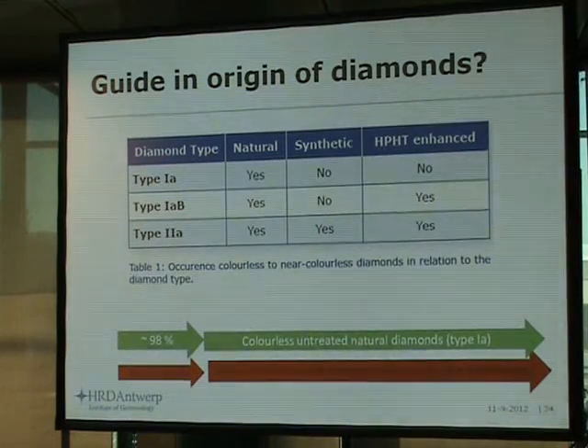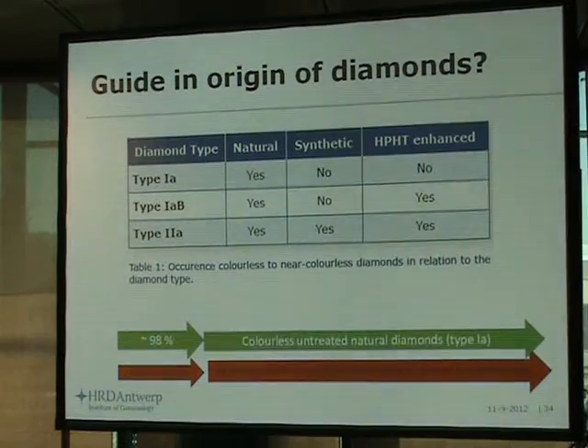Same accounts for 1AB. In a similar approach, you can see that these can be HPHT treated. So if you encounter 1AB diamonds with the machine, you have to look further to check if this diamond is natural or HPHT processed, with respect to the color and the origin of the color. And then type 2A diamonds, completely clear that these have to be referred anyway to a lab for further investigation. But at this stage, the good thing is that population-wise, only 1 to 2% of your goods are in that category, that range of goods that needs further testing.